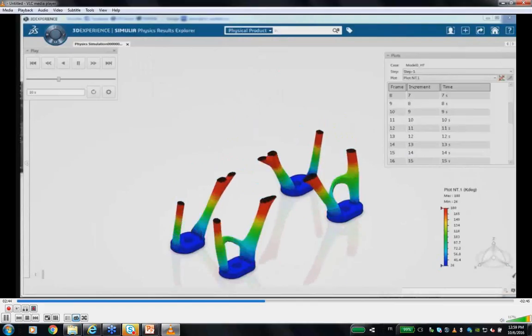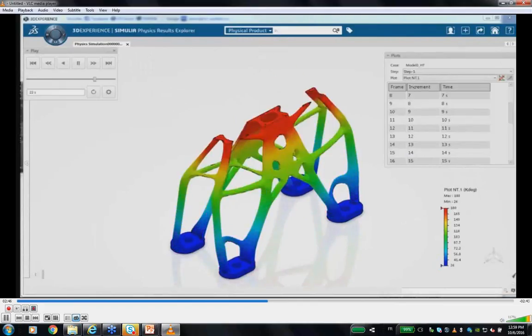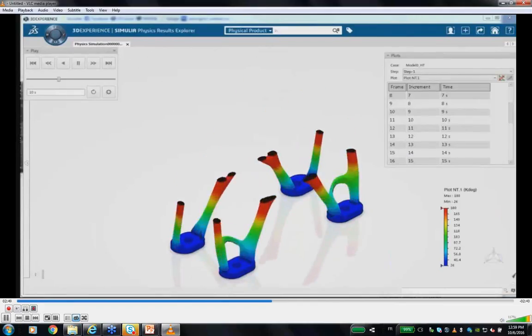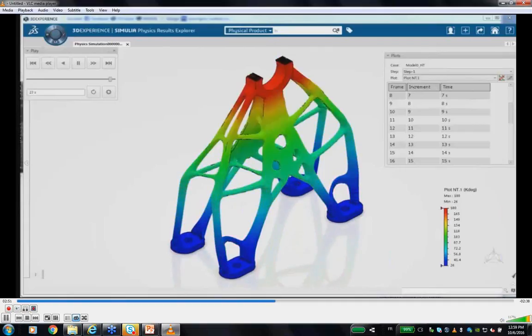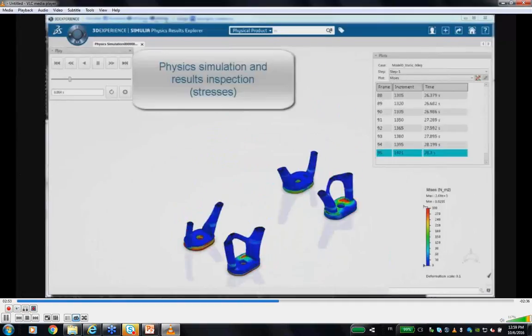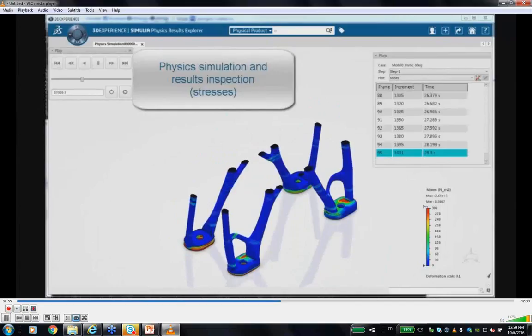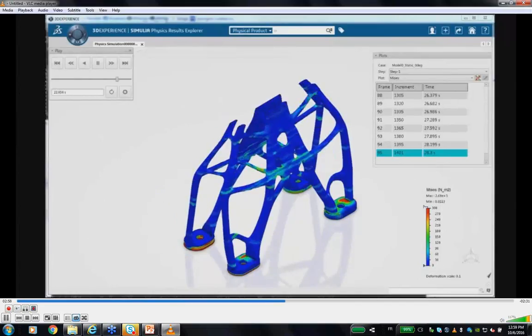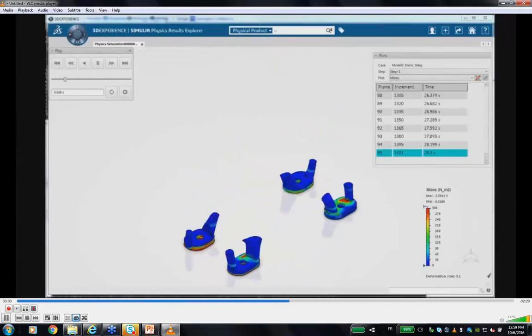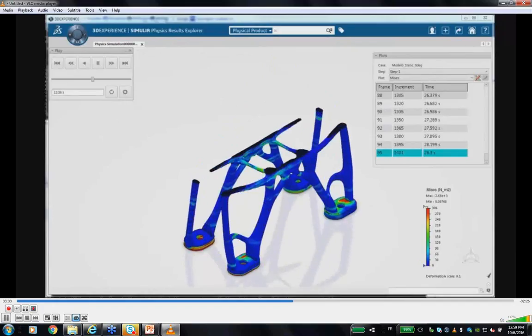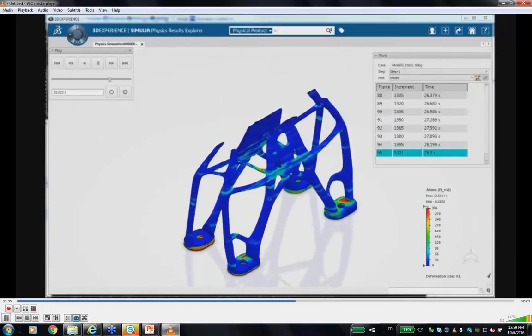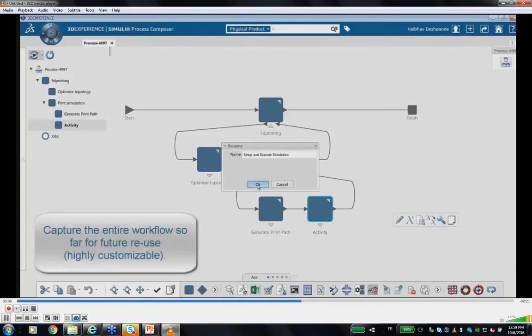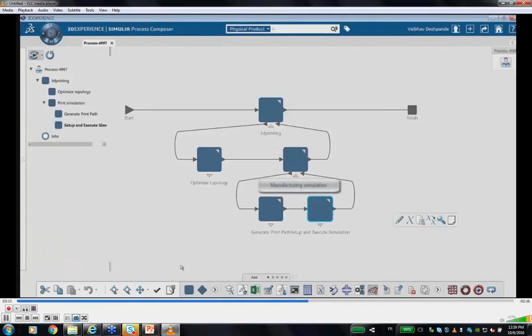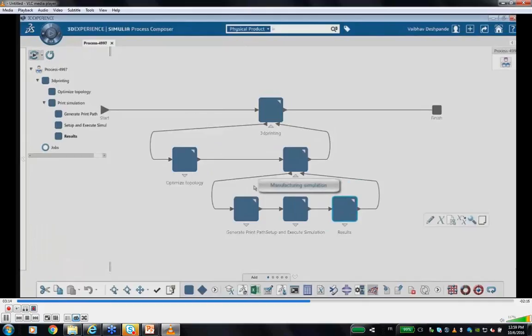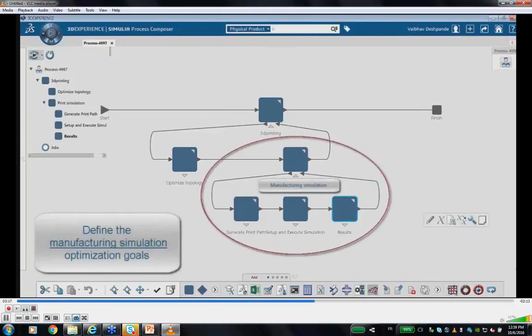And more important, not only does he perform a thermal analysis, but he can also couple the mechanics and compute a thermomechanical analysis. And from this thermomechanical analysis, I can have an idea of the stress inside the part. And from this stress computation, I can predict the distortion. Okay. So here, what we will do, we will also use Process Composer to optimize the process to reduce the distortion.